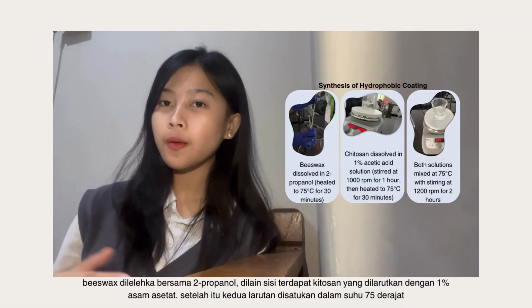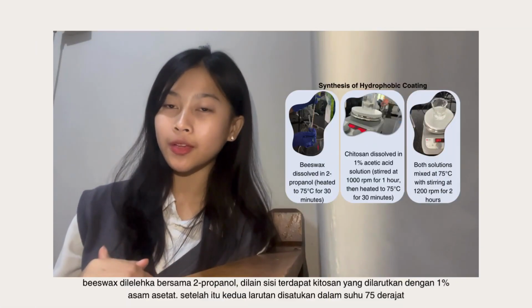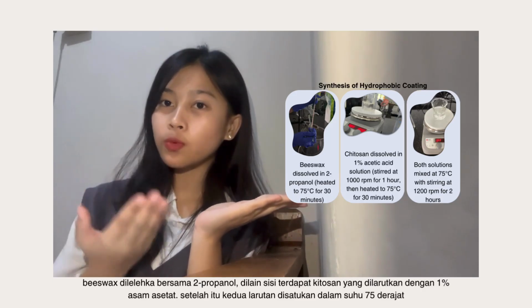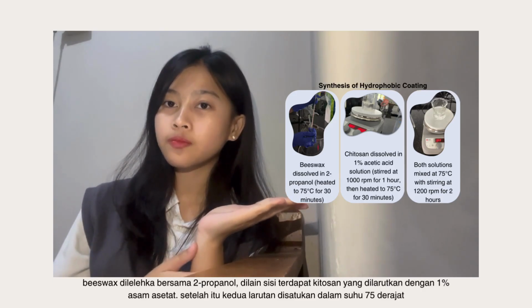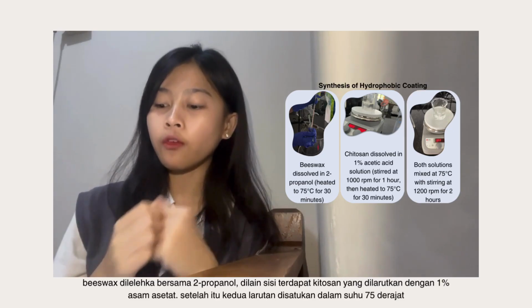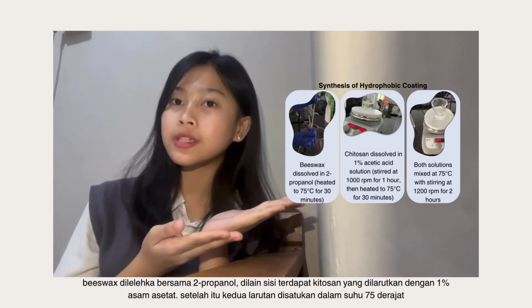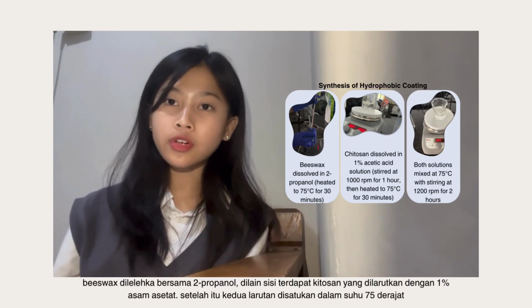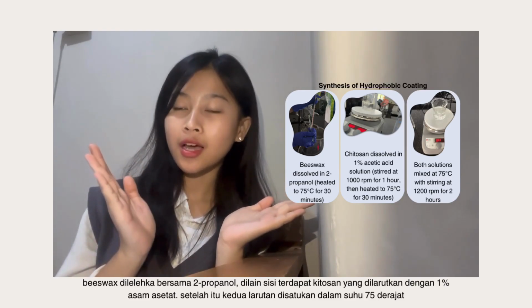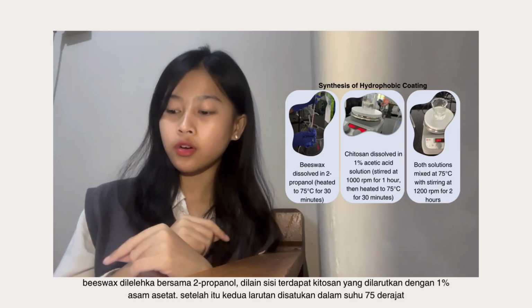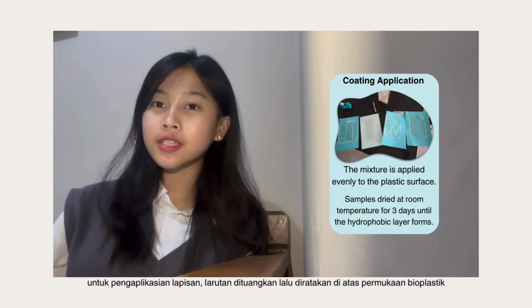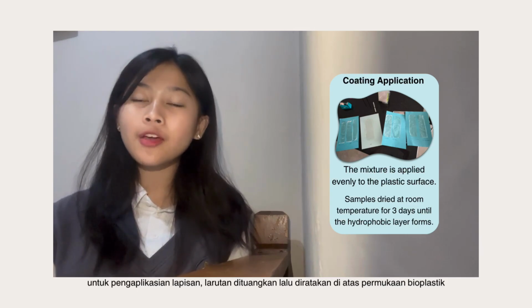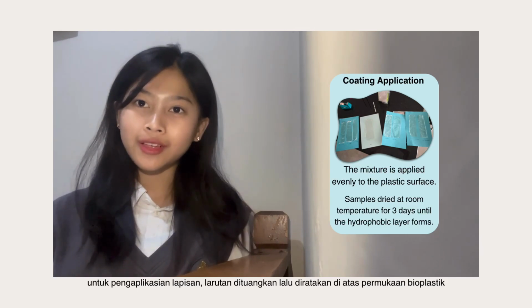The second step is synthesis of the hydrophobic coating. First, we have beeswax dissolved in 2-propanol, and in the other beaker, we have chitosan dissolved in 1% acetic acid. After that, beeswax and chitosan are mixed together. For the coating application, the mixture is applied evenly on the plastic surface.